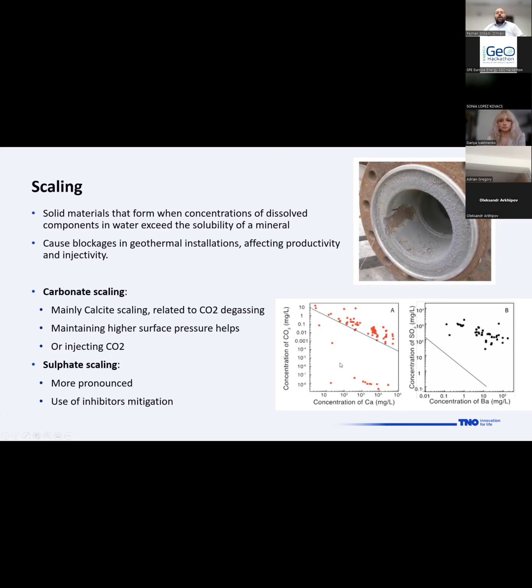Currently, mainly with the scaling inhibitors, they have been controlled. For the carbonate scaling, you can also inject CO2 to modify the pH and deal with that. But you already know that modifying the pH by injecting CO2 in the system to deal with the carbonate scaling means that you increase the risk of corrosion. And you have to find some optimum. So in the end, you inject CO2, your scaling problem is gone, you get a corrosion issue, and then you have to inject the corrosion inhibitors. And no problem, you can control it, but these are all costs.